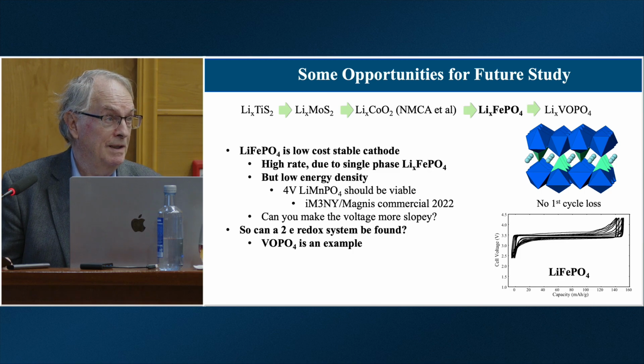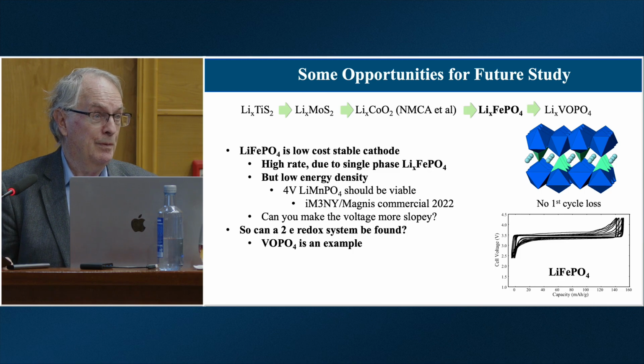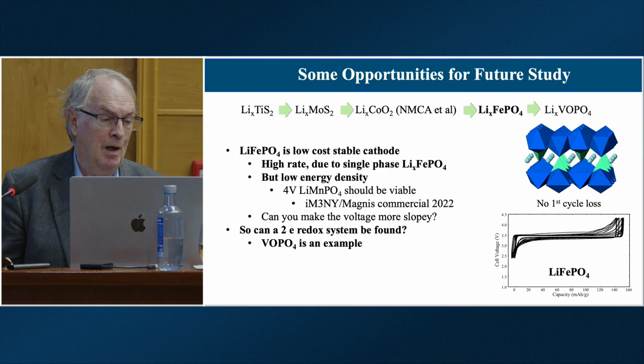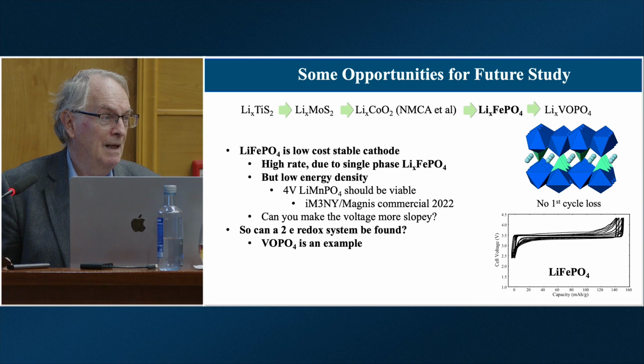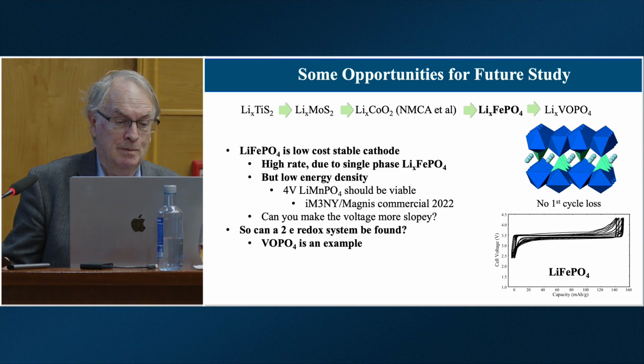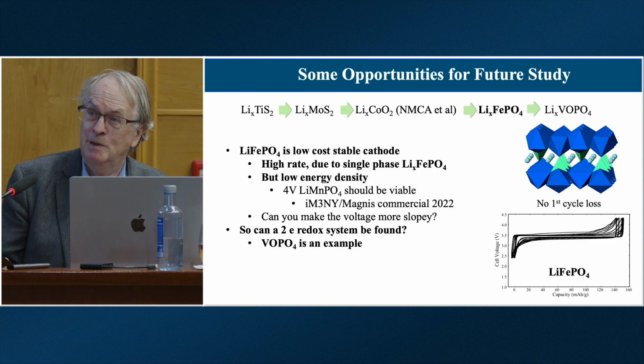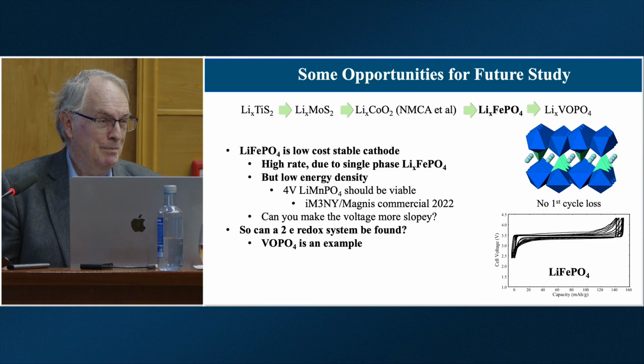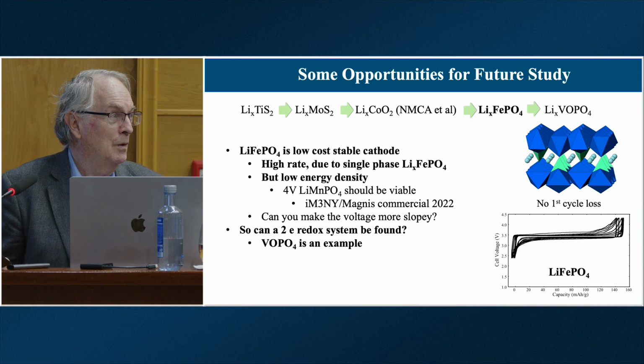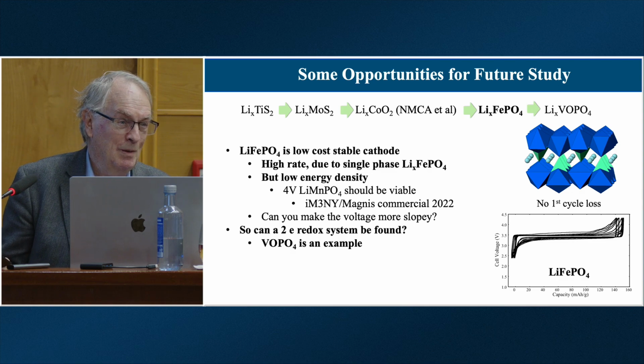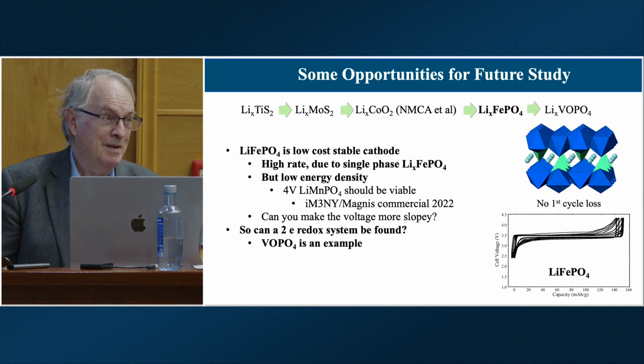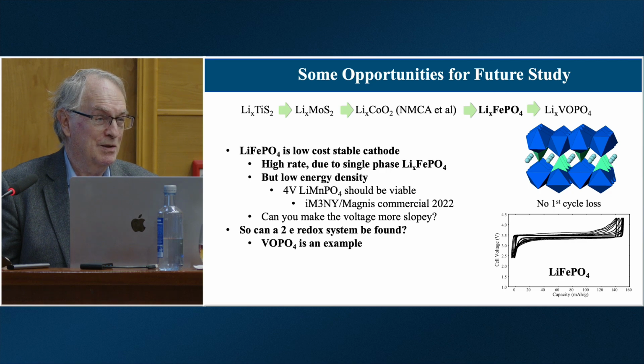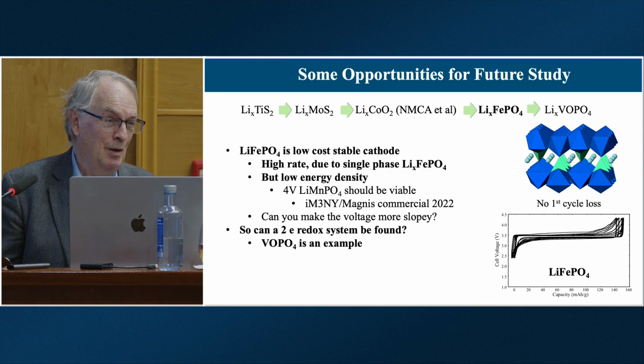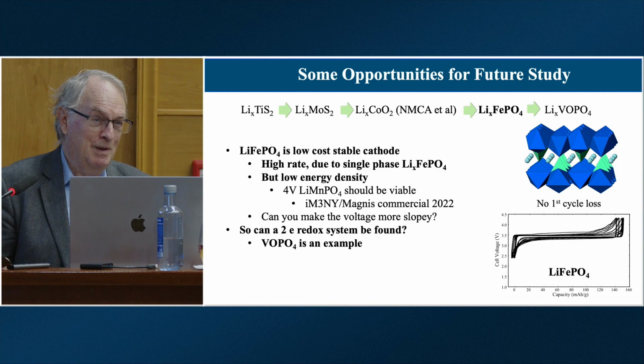One way of doing that is to change out the iron to manganese, so you go from 3.5 to 4 volts. And this is what our colleagues are doing across the street from us in Endicott, New York. They've just started up a gigafactory to make lithium manganese phosphate rechargeable batteries. But the challenge with these materials, you can see that's a nice flat plateau, which may be good for electronic devices, but it's awful to tell, are you 90% empty or 90% full? So you can't tell where you are on that curve. And if you read Tesla's operator's manual, some of their cars have this battery in them now. They say when you get home every night, plug it in, because you don't know whether you're empty or full.